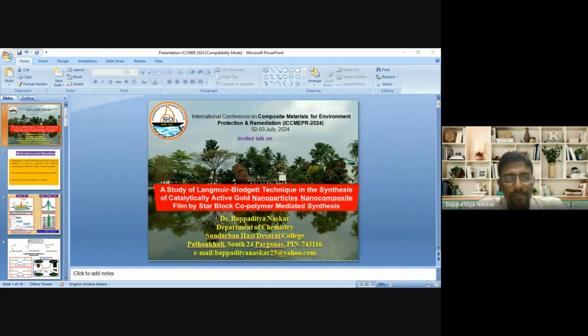Basically, a Langmuir film is usually made in a Langmuir trough, where a predetermined concentration of a nearly insoluble substance is spread. It is an amphiphile, having both hydrophobic and hydrophilic parts. Initially it is dissolved in something like chloroform or a chloroform-ethanol mixture, which evaporates as the spreading solvent. When we compress the two barriers, we can create a monomolecular film, and that becomes a Langmuir film.